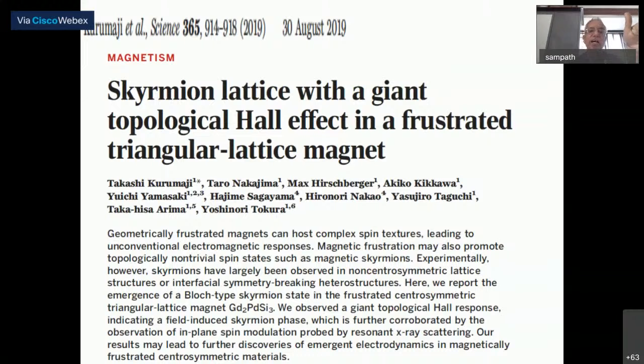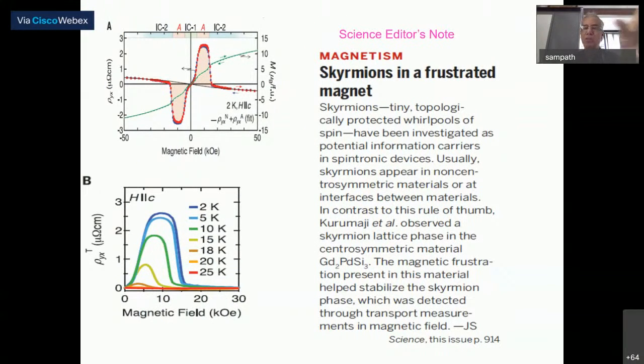They measured the Hall effect again, which is now called topological Hall effect, and they find skyrmions. I will credit them for finding skyrmion behavior in this material by resonance scattering measurement. So the intermediate field gives enhanced Hall effect, which is now called topological Hall effect. As all of you know, topological Hall effect was for the first time experimentally recognized in magnetic materials in manganese silicon and iron cobalt silicon in 2009. This was 10 years after we produced these results, and at that time the concept of topological Hall effect did not exist. When we said that it's a very complicated magnetic structure, these authors find the skyrmion lattice, and we are very pleased. However, the fact that we measured Hall effect was not explicitly mentioned in our paper.